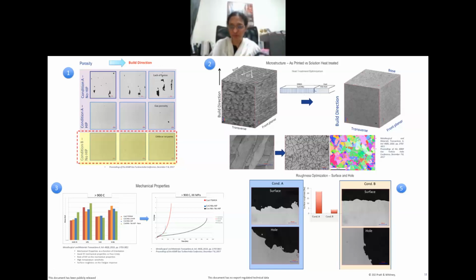Despite doing a design of experiments, the challenge we are facing is the lower sensitivity of the design of experiments in telling you which energy density you can choose. For example, we get at least 5 or 6 energy densities, with laser power, scan speed, layer thickness, etc., giving the same dense microstructure, at least at the optical level, which matters going forward in terms of making the part to the section thicknesses that are needed, or variable section thicknesses, mimicking, let's say, this aero engine blade.